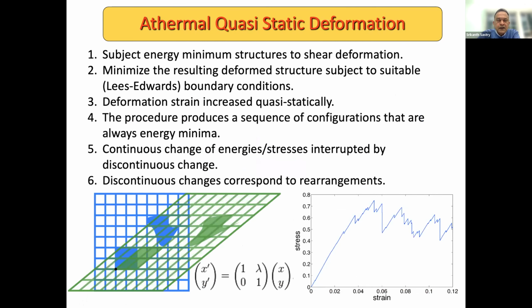So I mentioned athermal quasi-static deformation. Just to say two words about it, what one does in this procedure is to subject energy minimum structures to shear deformation, and one applies a shear strain, and the resulting deformed structure is subjected to energy minimization. And so this produces a sequence of configurations that are always energy minima.